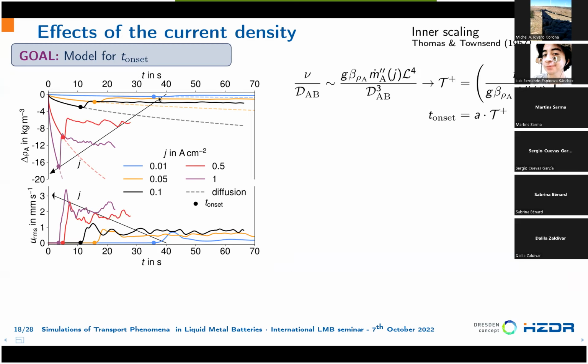And from the theory of thermal convection over a heated plate, we know that there is a scaling that in the literature is referred to as inner scaling. This inner scaling is practically a balance between diffusive forces and the buoyancy part. And this inner scaling works with the assumption that the height of the layer has no influence on the phenomena that we are observing at the beginning. And from this, we can derive a time scale.